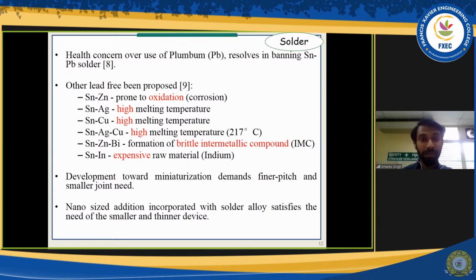Other lead-free solders that are being studied are tin zinc (SnZn), tin silver (SnAg), tin copper, tin silver copper, tin zinc bismuth, and tin indium. I've listed what the drawbacks of these particular lead-free solders are. They are lead-free, but I can see that these have certain problems. For example, let's take a three-element one, which is SnAgCu. This is the most studied solder currently, but it has a high melting temperature of 217 degrees Celsius. That is around 20 degrees near to the expected soldering temperature, so there might be a problem during the soldering process.